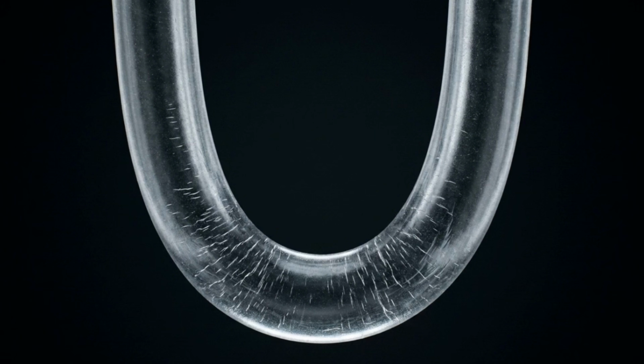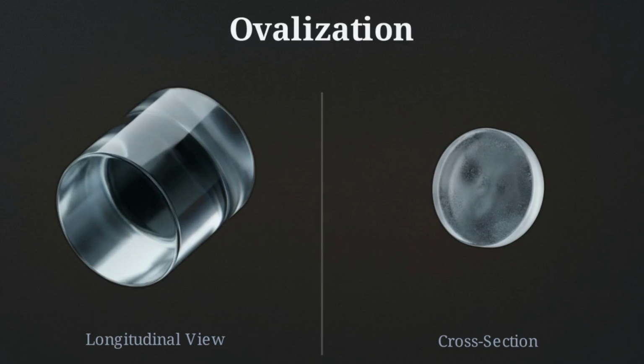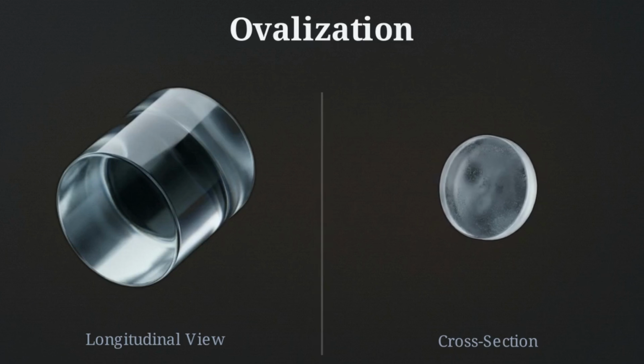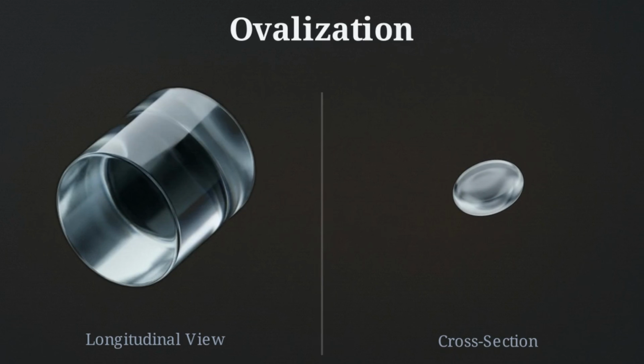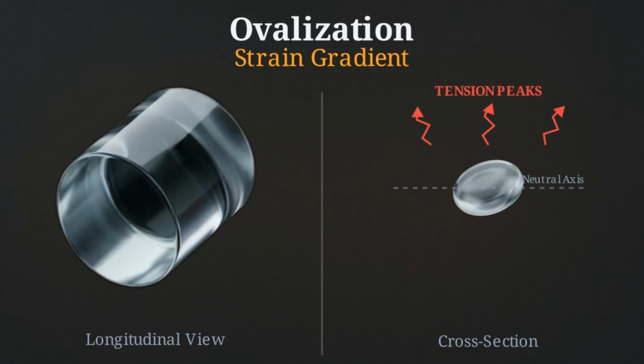When we force a rigid line to bend sharply over itself, we are moving the material far beyond its simple tensile limits. This causes a phenomenon called ovalization. As the line bends, its circular cross-section flattens under the pressure. This flattening creates a severe strain gradient. The outer edge stretches to its limit, while the inner edge is crushed by intense compression.